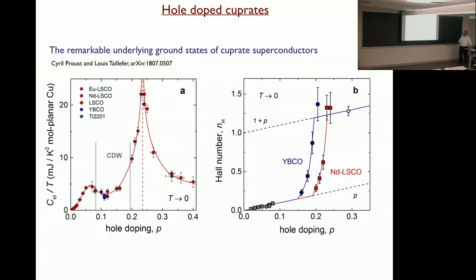More recently, there's another indication that something similar is going on. This is, for example, the specific heat. The specific heat is linear in temperature in any metal. In this case, I think you measure the specific heat by applying a magnetic field to suppress the superconductivity. If you go to high doping, you get some gamma coefficient, as it's called. But right near this 20% or so, they get a fairly well pronounced peak. Is this really a peak at low enough temperatures, or is this just rounded out because of disorder? Well, these are questions you can decide for yourself by looking at the data.